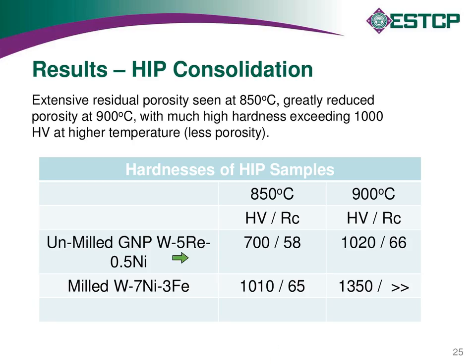So here's where we started looking at some of the de-agglomeration process. This is the milled powders. After going through the GNP process to produce, in this case, a tungsten nickel iron composite powder, it was then wet milled to de-agglomerate the powders so we could improve the packing densities in these materials. And with some success. What you notice is normally you don't see the hardness going up at the higher sintering temperatures or higher hot isostatic pressing temperatures, but these numbers here at 850 are low because there's still a fair amount of residual porosity in the material, while this is closer to the true hardness of the material when we're getting closer to full density.